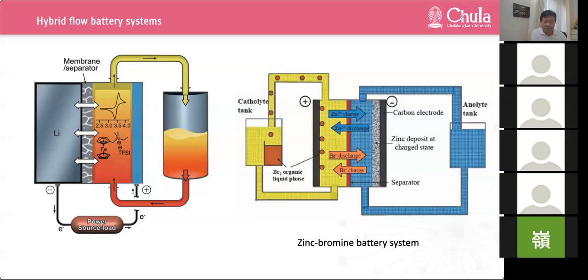However, demonstration of the zinc bromine system has been limited because of material corrosion. You can expect that, because bromine is corrosive. And we also have the problem of dendrite formation and electrical shorting, high self-discharge rate, low energy efficiency, and short cycle life. The existence of corrosive bromine at the cathode side is the cause of some of these problems. So expensive cell electrodes, membranes, and fluid handling components are needed to withstand the chemical conditions of bromine, which is corrosive. And the other thing is bromine has limited solubility in water, and it's of course toxic.